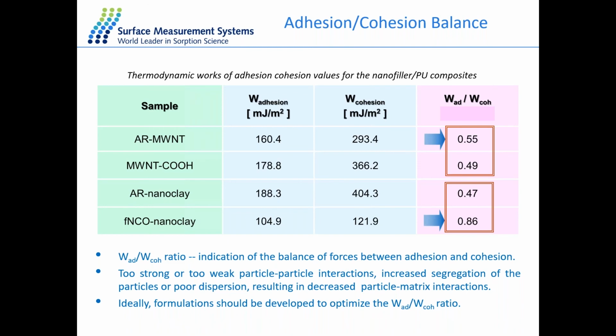So in this case, it's a good indication of the balance of forces between the adhesion and forces of cohesion. And this is quite important in formulation studies because if you have too weak or too strong particle-particle interactions, this can either lead to segregation or aggregation of the material. And this can lead to maybe poor dispersion into the polymer matrix. So it can be used as a formulation tool prior to making any final products. And we can develop and optimize the work of adhesion and cohesion ratio.